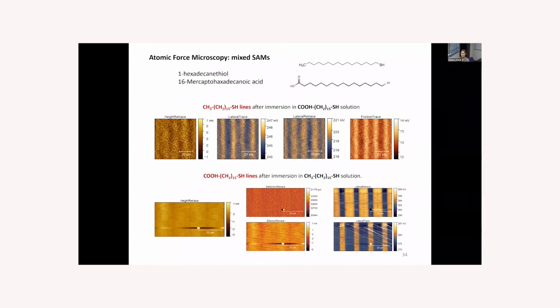We have also made the mixed samples. That means that first we create a patterned surface of one of the molecules, in this case, methyl group, and then we immerse this patterned surface in the solution of another thiol, in this case, the carboxylic terminated thiol. And you can see this was successful. We have also done it the other way around. We have immersed the patterned lines of carboxylic acid terminated surface in the methyl terminated alkanethiol solution, and we obtained very nice results by AFM.